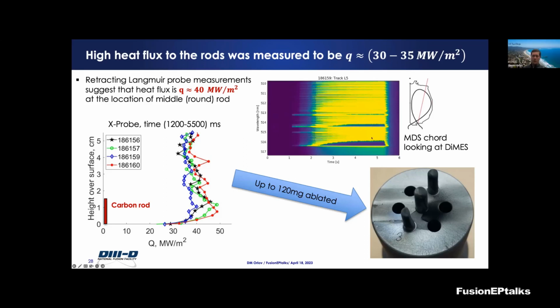We could see a lot of ablation in the multi-chord divertor spectrometer, MDS. This is chord 5 in this case, looking directly at the DIMES port, and you could see a lot of emission in the wavelength range between 510 and 517 nanometers during the whole time of the exposure of those rods to the high heat fluxes.